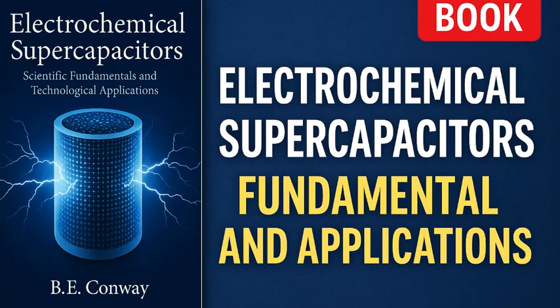To break past that barrier, designers turn to non-aqueous electrolytes, typically organic solvents with dissolved salts, or even fused salts known as ionic liquids. Using organic electrolytes, modern supercapacitors commonly reach around 2.5 to 2.7 volts per cell, and some ionic liquid based lab devices can operate at 3 to 4 volts. What's the trick? Organic solvents like acetonitrile or propylene carbonate have much larger electrochemical stability windows than water. For instance, acetonitrile with a suitable salt might be stable to 2.7 volts before it oxidizes or reduces.